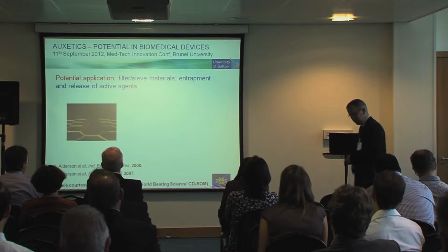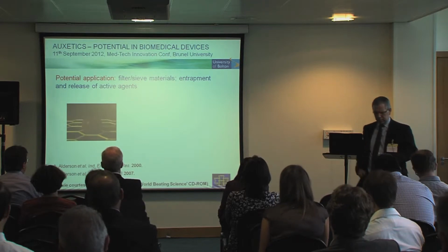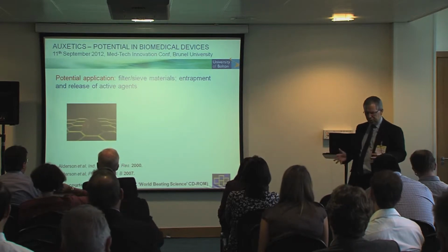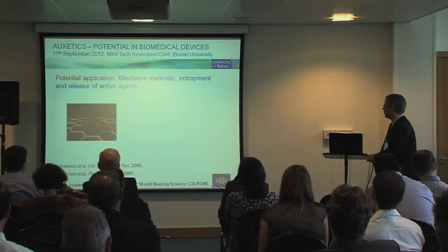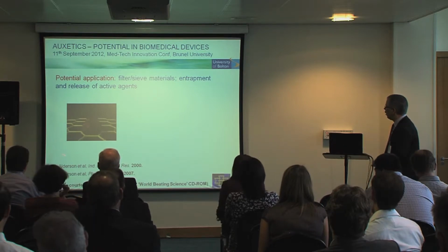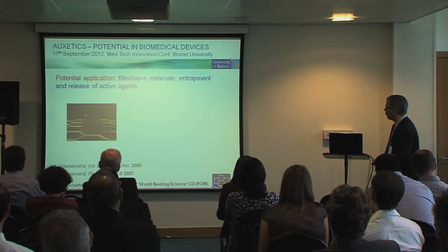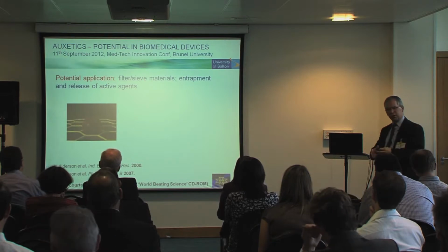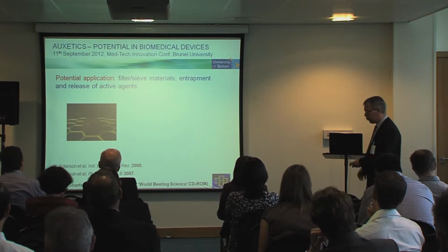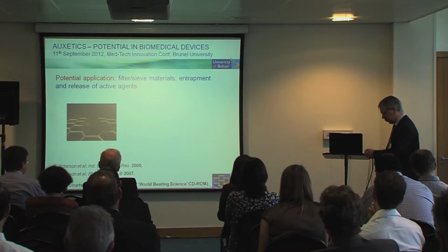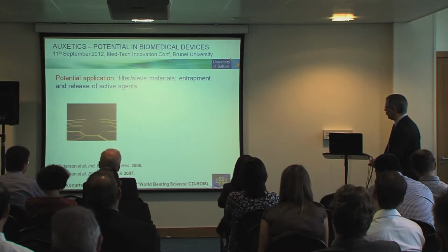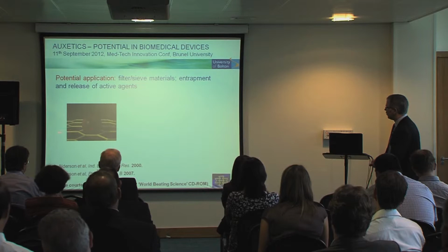Another area we've looked at is the effect on the change of porosity in a porous auxetic material. So this is a normal non-auxetic honeycomb. We've got a particle block in it here, and if you want to clean that membrane by pulling it mechanically to open up the pores, it's not possible. The pores close up in one direction as they open up in the other.